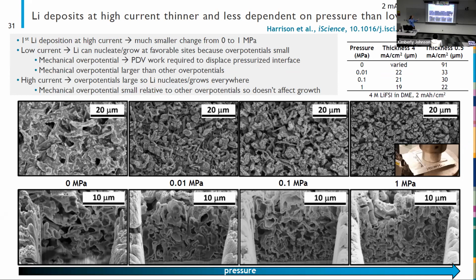But what's striking about these images is if you recall what I showed you at low current density, we saw a huge variation in the thickness of the deposits and the morphology with pressure. And we don't see that at all here. We really see very little difference with pressure in how the deposits look and the thickness of those deposits. So why is that? We've thought about this a lot.